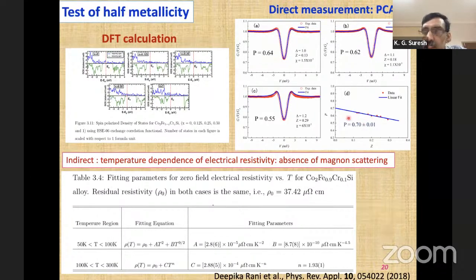So you have only low temperature data. You cannot get a PCAR at room temperature under the existing superconducting materials. So that is a severe limitation as far as the PCAR data is concerned.